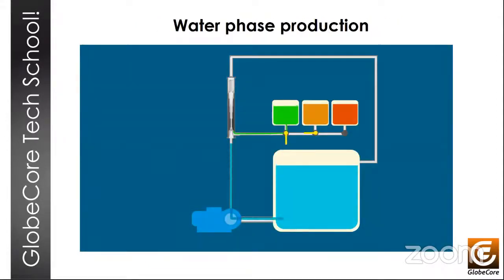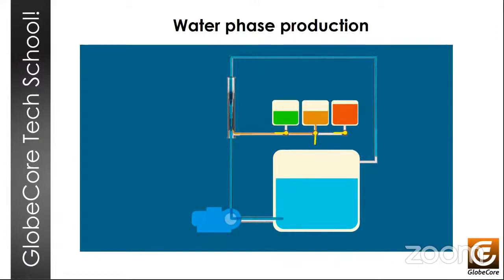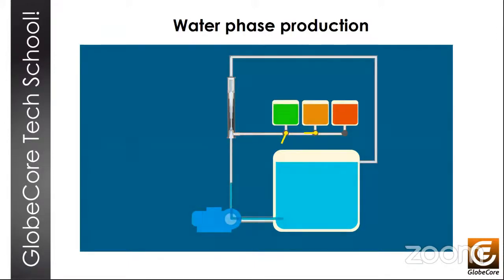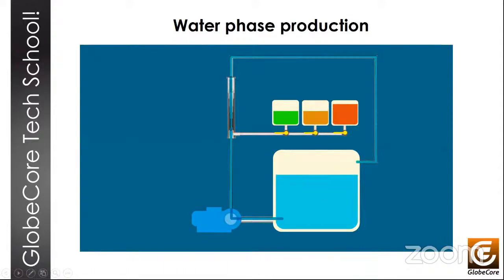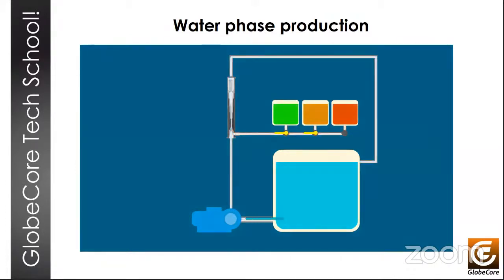Here is the water phase production. When we circulate water in the tank, this pump draws in the necessary components through the mixer. The components are supplied one by one sequentially by opening the valves of the measuring containers to obtain a water solution of the emulsifier. This way, in our plant, we make a concentrated emulsifier solution, which instantly forms an aqueous phase with specified characteristics, mixing in the required proportions with water heated to the process temperature. This water phase is prepared immediately before mixing with the bitumen phase, and it flows from its mixer to the mixer for the bitumen emulsion.